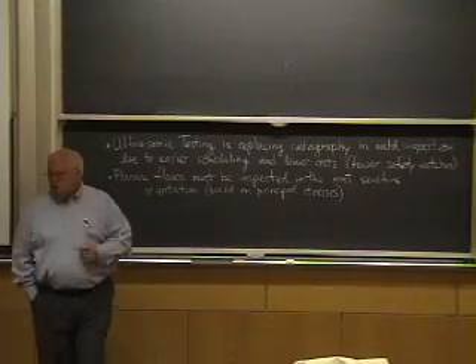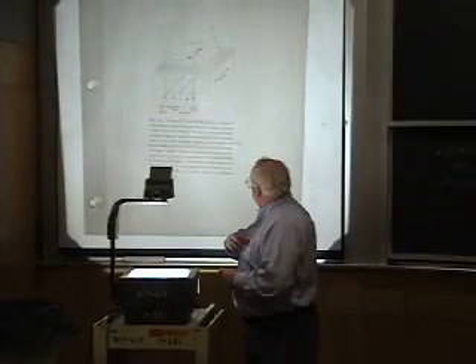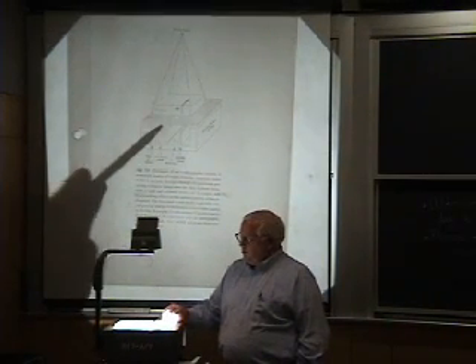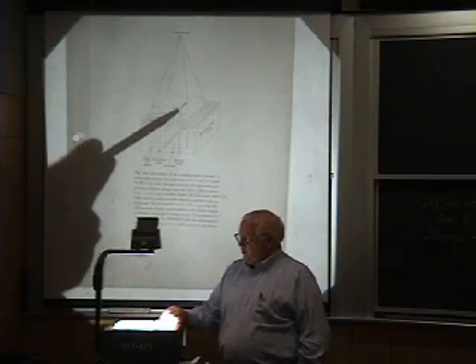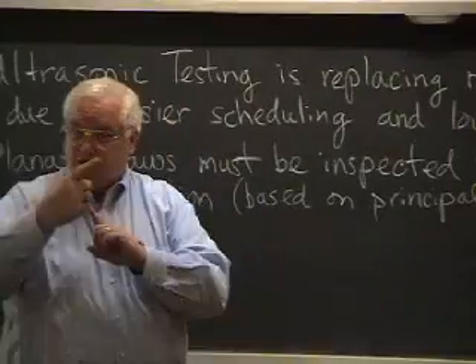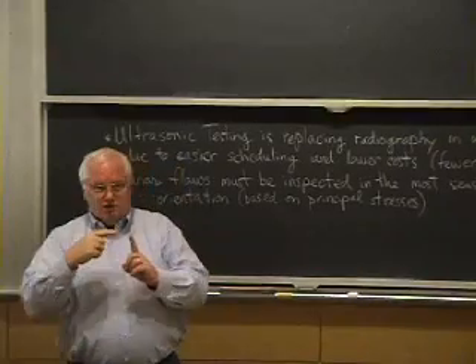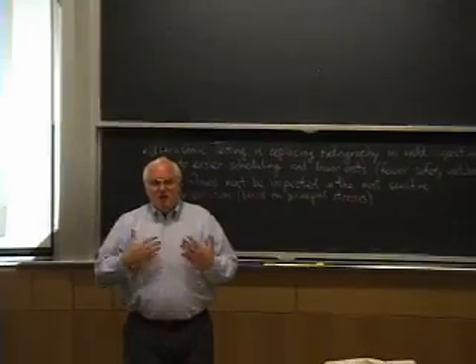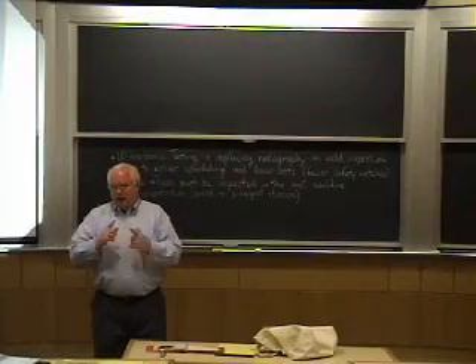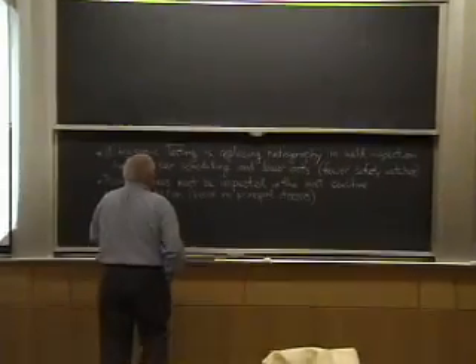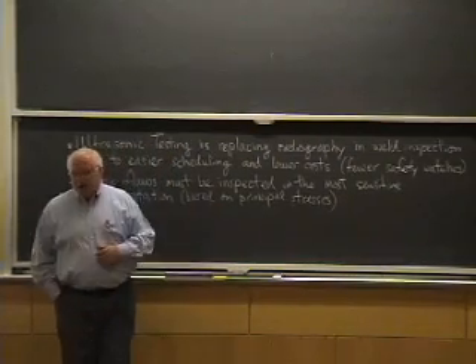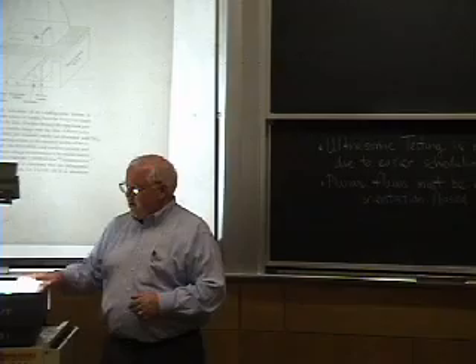Planar flaws have to be inspected in the most favorable orientation for finding them. I put up this overhead showing that for X-rays, if you have a planar flaw in this orientation, it's hard for the X-ray to see it because that orientation isn't as large a fraction of the thickness as this orientation. However, what you're really interested in is a planar flaw that's oriented in the direction of the maximum principal stresses, or any major principal stresses. Remember, stress is a tensor, but if you're talking principal stresses, you're talking about 3 dimensions, right? X, Y, and Z coordinates. And any direction in which you have a very large stress, that's where a planar flaw is liable to progress into a crack. So you have to be careful about that. That's true both for X-rays and for ultrasonics.